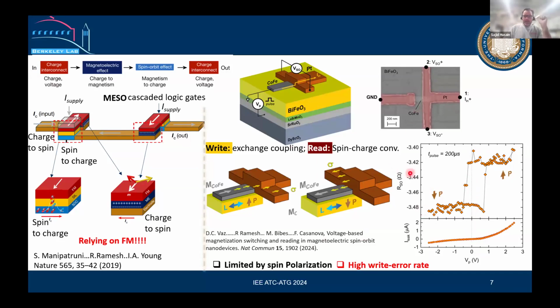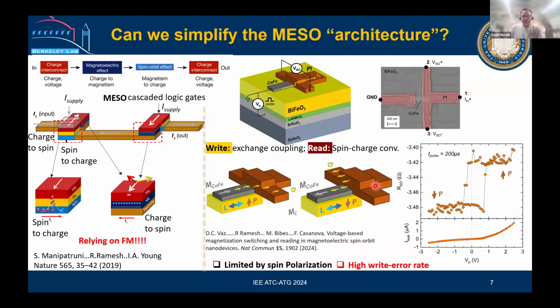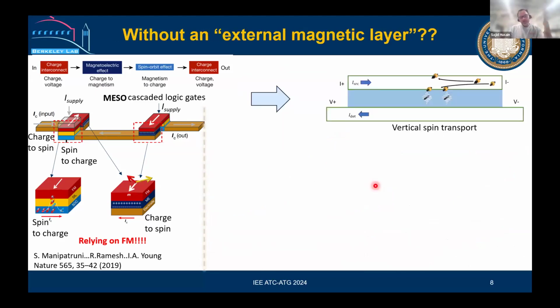But this device has some issues. It is limited by the spin polarization of the ferromagnet, because as I said, we need 100 millivolt output, but if you calculate this back into voltage, it is about 100 microvolt. So we still need a three-order-of-magnitude enhancement. There is also a high error rate, because your BFO is connected with cobalt iron, so sometimes you miss the switching of the cobalt iron by switching the magnetization or antiferromagnetic vector in BFO using the electric field. So it's a high error rate and a limited polarization by the ferromagnet. Then I entered this field to simplify the structure further, and what we did here as a group is we removed everything.